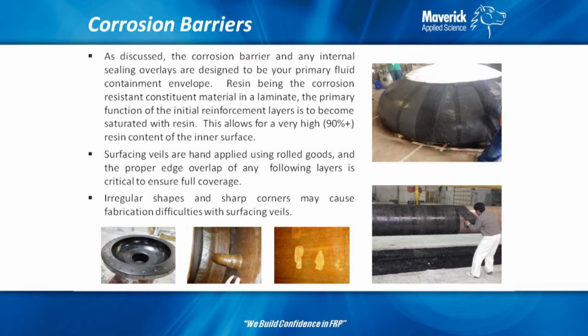So again, it's difficult to see, but you can see wrinkles in there where the carbon veil is trying to form around that knuckle. If you're putting it on a mandrel, typically it's not hard. You have to make sure your overlaps are right. Overlaps are critical, especially with veils. But on mandrels and flat surfaces, all these veils are fairly easy to apply.